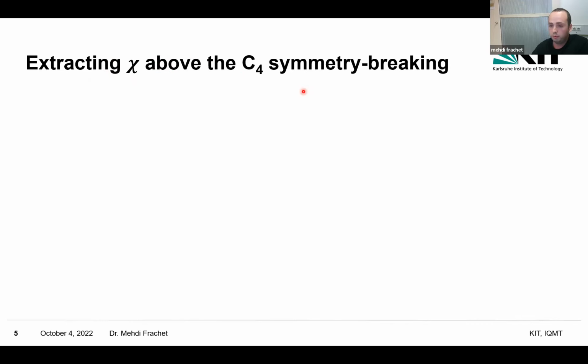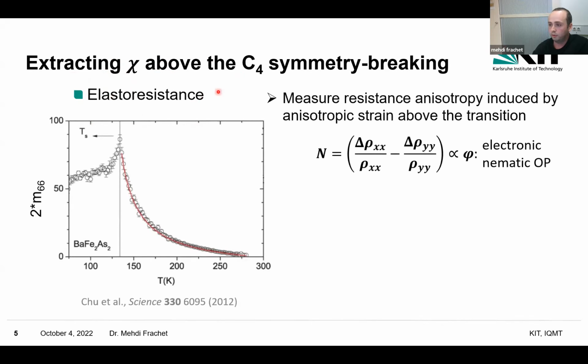There are different ways to do that experimentally, but one of them, and that's the focus of this talk, is the elastoresistance measurement. I'm showing you this paper from Jiun-Haw Chu and the group of Ian Fisher at Stanford. This was already done 10 years ago in barium iron 2 arsenic 2. In this really beautiful experiment they measured the resistance anisotropy induced by anisotropic strain above the nematic transition. What is really nice about this resistance anisotropy is that under certain circumstances, it's a good proxy to the electronic nematic order parameter.